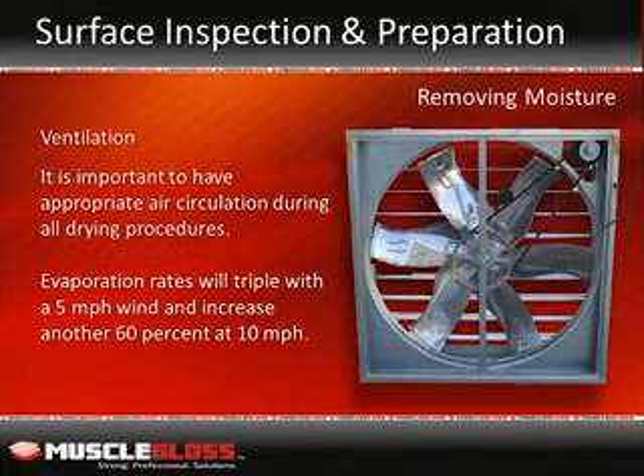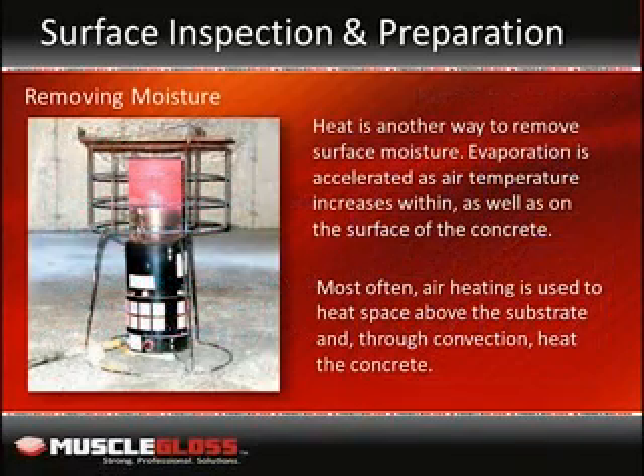It is important to have appropriate air circulation during all drying procedures. As moisture rises to the surface, air movement at the surface will carry it away and promote evaporation. Evaporation rates will triple with a 5 mph wind and increase another 60% at 10 mph. Heat is another way to remove surface moisture. Evaporation is accelerated as air temperature within as well as on the surface of the concrete increases. Heat moves water and solid materials, allowing it to move to the surface and evaporate easily.